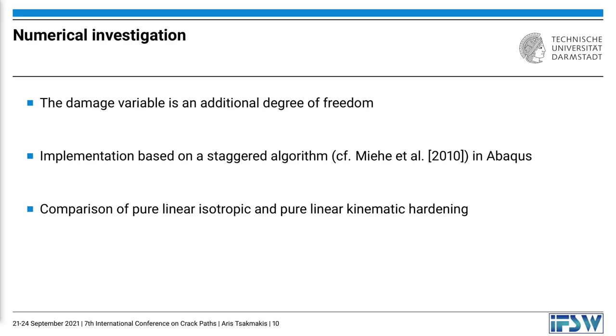With this material model at hand we move over to the numerical investigations, which were performed in the finite element framework. The damage variable is introduced as an additional degree of freedom in the model, and the implementation in Abaqus is based on the staggered algorithm, meaning that the displacement problem and the phase field problem are solved independently. First the phase field is held constant and the displacement field problem is solved, then the displacement is held constant and the phase field problem is solved, and the two steps alternate until convergence is achieved in the respective time increment. For the present work we compare results for pure linear isotropic hardening and pure linear kinematic hardening.